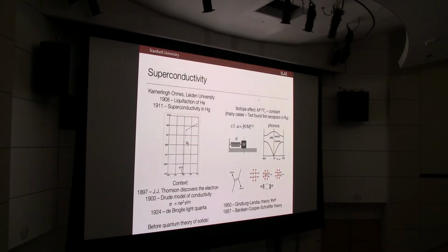But this picture led to the simple association that if I remind you of a harmonic oscillator, a mass on a spring, the resonant frequency goes as the square root of the spring constant over that mass. And this square root of this ratio also sets a scale, for example, in a ball and spring model for the sound velocity in terms of the acoustic branch of phonons. So this was one of the key experiments that led to the thinking that phonons and electron-phonon coupling must be intimately related to superconductivity.